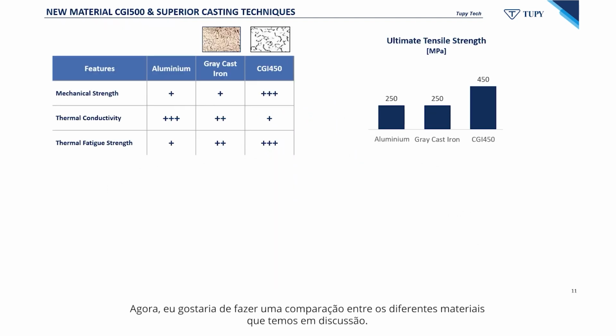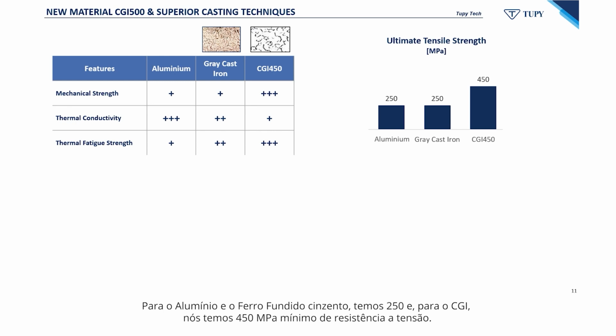Now I would like to do a comparison of the different materials which we have in discussion. You see the comparison of aluminium to normal grey cast iron and to CGI, here the grade 450. Cast iron and CGI 450 have higher mechanical strength than aluminium. The thermal conductivity is for aluminium the best in this comparison. With regard to thermomechanical fatigue strength, CGI 450 has by far the best values. Please see the ultimate tensile strength values on the right side. For aluminium and grey cast iron we have 250. And for CGI, we have 450 megapascal minimum tensile strength.